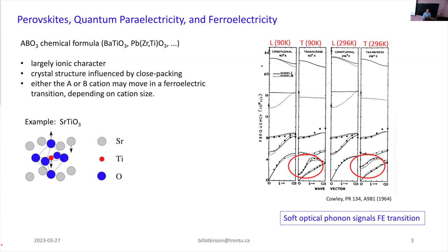And so the titanium has a little bit of room to move. And so the cartoon of why ferroelectricity happens in strontium titanate is that the titanium can lower its energy by moving slightly off center towards one of the oxygen sites.